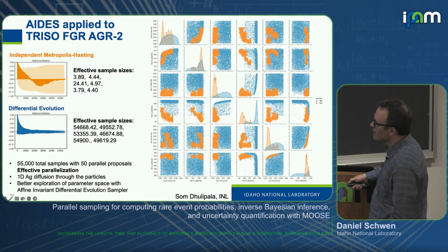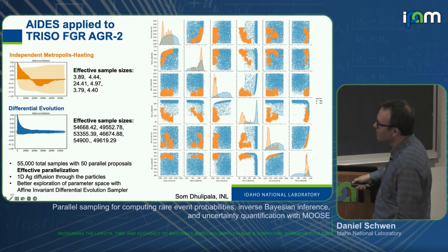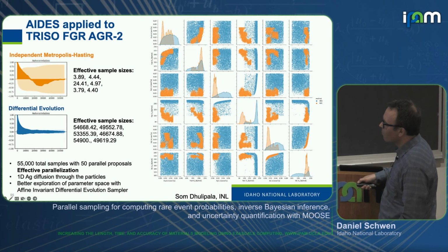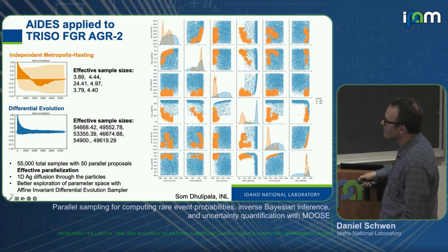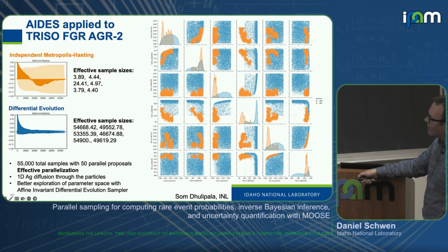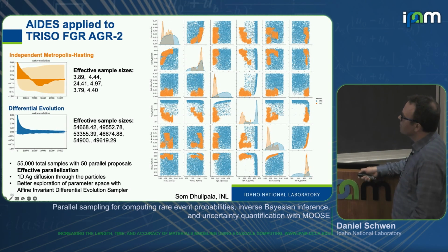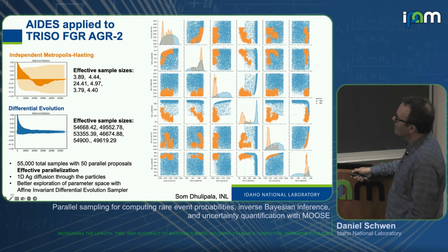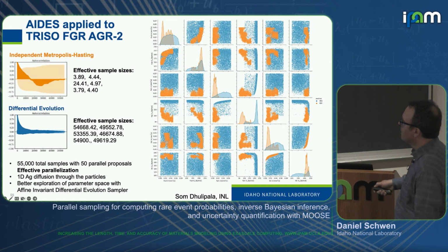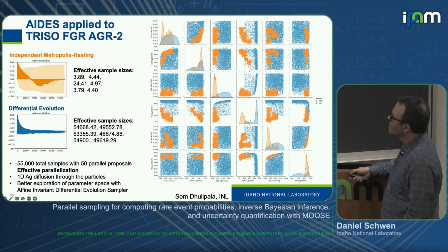These autocorrelation plots are a little misleading the way they are plotted, because what you're seeing here is basically every 50th sample from this parallel Monte Carlo walk, which has a bit more autocorrelation than all the other samples. So the effective sample sizes are orders of magnitude higher when you do this differential evolution. And you can just immediately see that you're exploring the parameter space much better suddenly. And your distributions now look smoother and so on and so forth. But really still super wide.